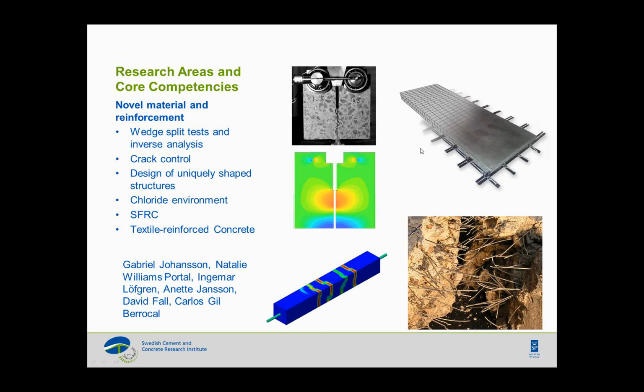And lastly, we also work with simulation-aided damage assessment in concrete structures. In particular, we have been working for a long time with the modeling of the swelling effect of corrosion. We have also been working with multi-scale modeling of coupled chloride moisture diffusion. I would say corrosion is what we have really been working with for a long time, but we also work with frost damage, with sulphate attack, and with ASR. So from now on, I'm going to be focused on the simulation-aided damage assessment in concrete structures.